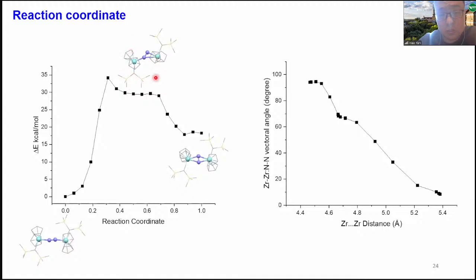It undergoes the first transition going to what we call a triangular structure, right? So this zirconium binds to one nitrogen, the other zirconium binds to two nitrogens. And from here, there's really a shallow barrier that transitions to the side-on structure.